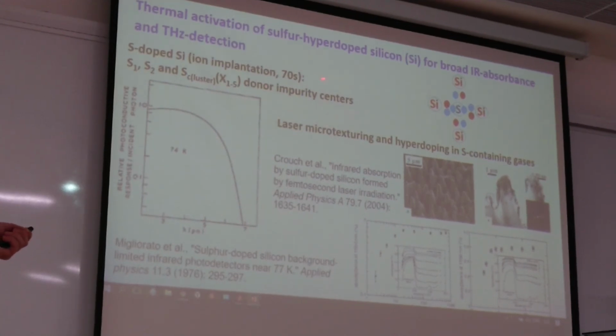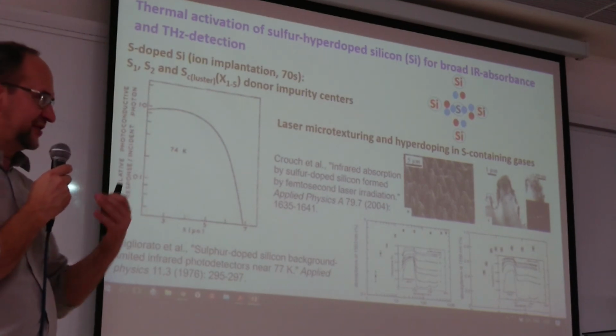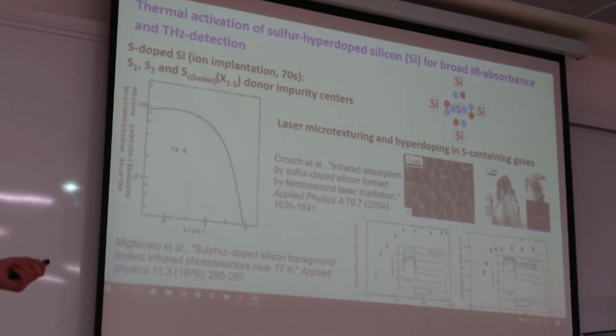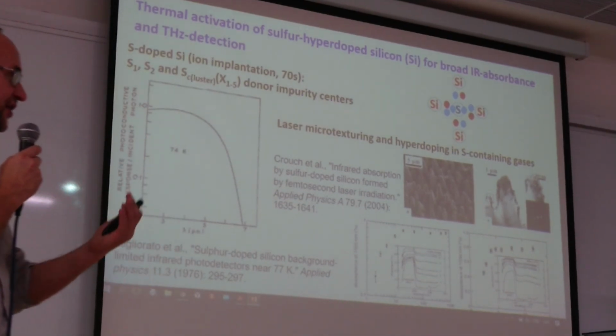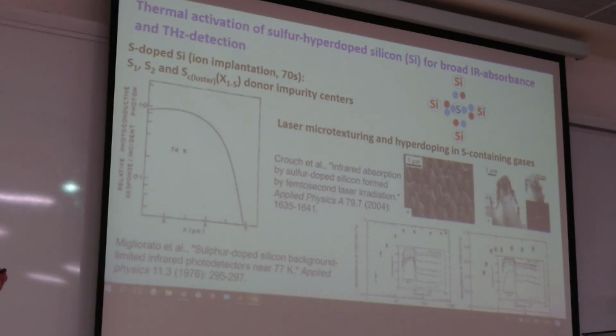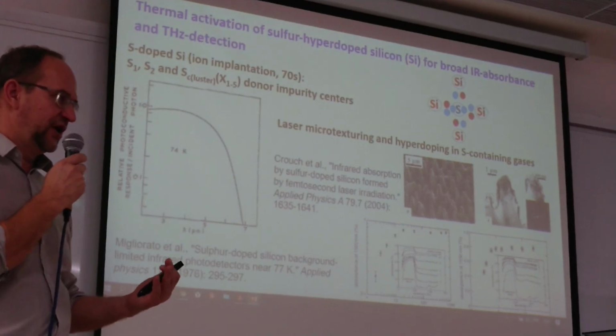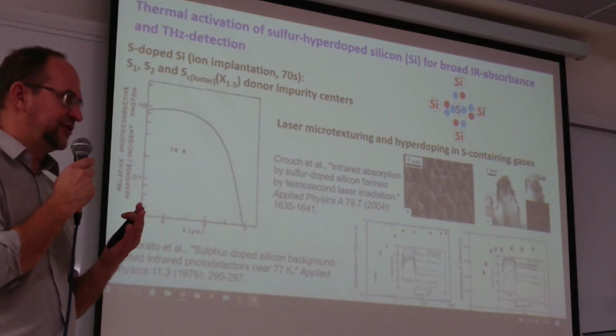Since the 70s of the last century, it was known that sulfur can dope silicon through ion implantation, so we can introduce donor sulfur impurities into silicon. We can produce atomic centers, diatomic centers, and cluster centers like this. And these centers make a very important change in silicon properties. Typically, silicon is blind in the infrared range. So silicon photodetectors operate only in the visible range, and in the infrared range they are blind, they cannot detect anything